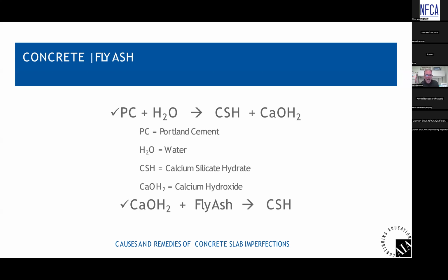And what the fly ash is doing, once the cement and water react and create the byproduct called calcium hydroxide, the fly ash that's in the concrete reacts with that lime in the concrete, that byproduct, and it creates additional calcium silicate hydrate.